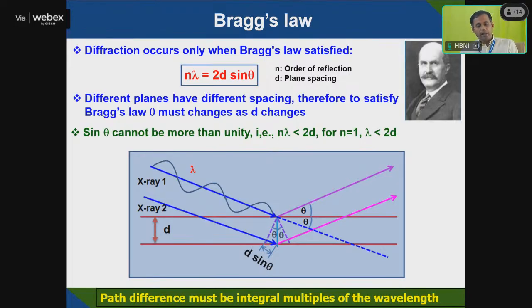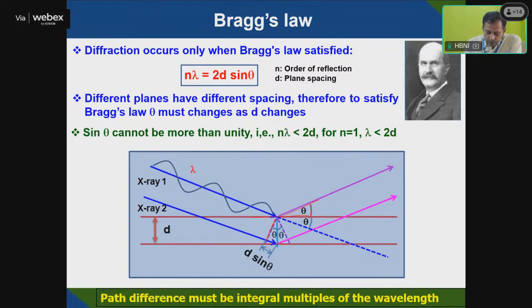So whenever Bragg's law is satisfied, that means n lambda equals 2d sine theta, then you will be able to see a particular peak. If you see here, the red line is the crystal plane on which the two X-rays, X-ray 1 and X-ray 2, are falling. After falling here, at this angle theta, it moves out. And the second one is coming here, and if you draw a perpendicular from here to the first plane to the second, this is the phase.